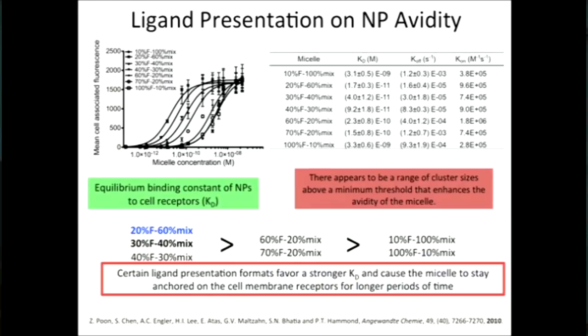And what we did was we functionalized the dendrimer to varying degrees. We have 16 end groups, and we varied the degree of functionalization from 10% to 100%, which means we went from 1.6 on average folates per dendrimer to 16 on average folates per dendrimer. Everything's on average because this is the real world and we're doing chemistry, so it's stochastic. However, it gives us a general idea of what's going on.